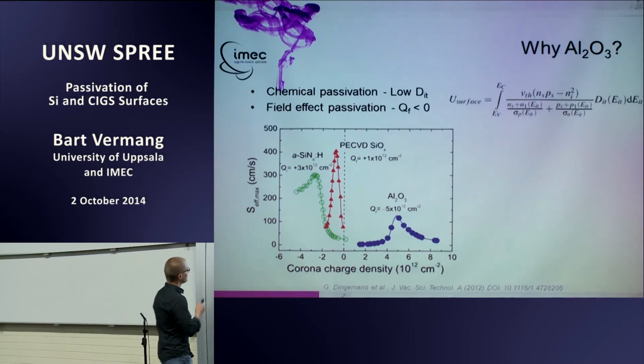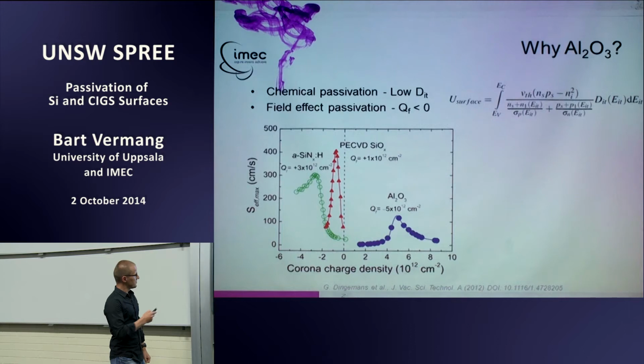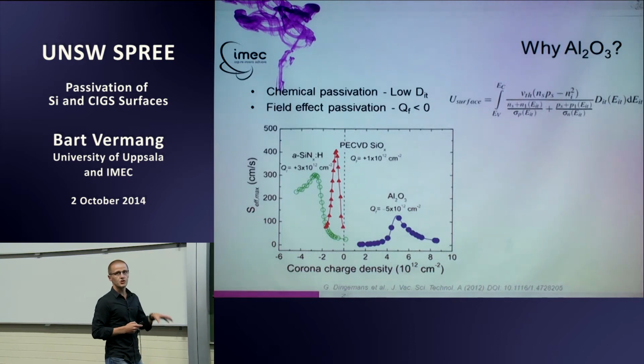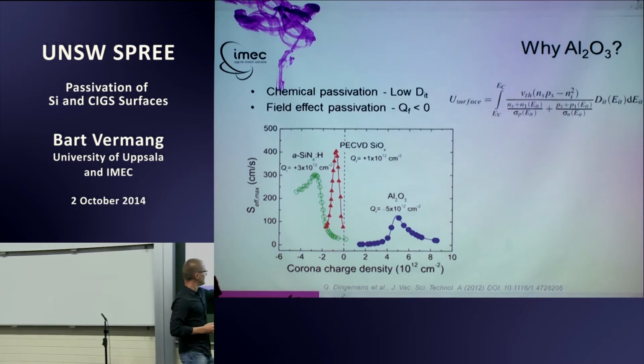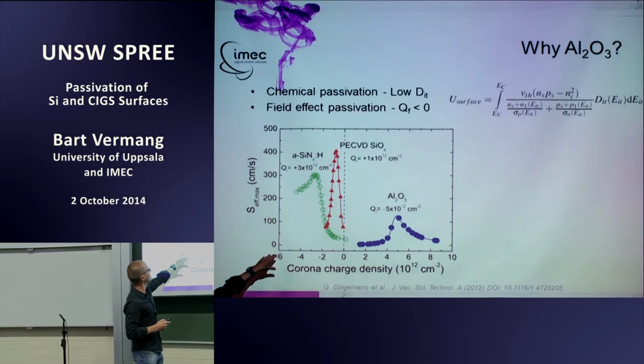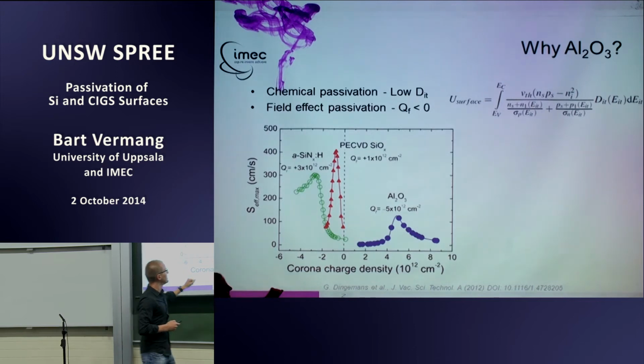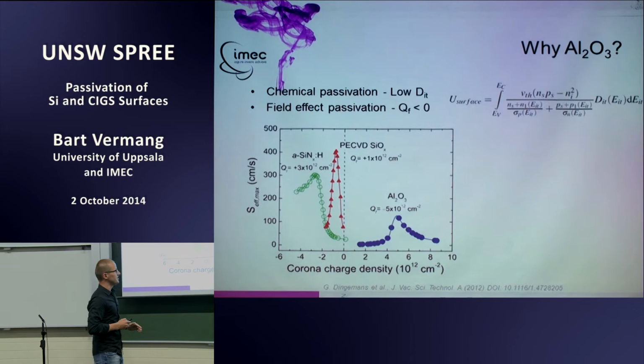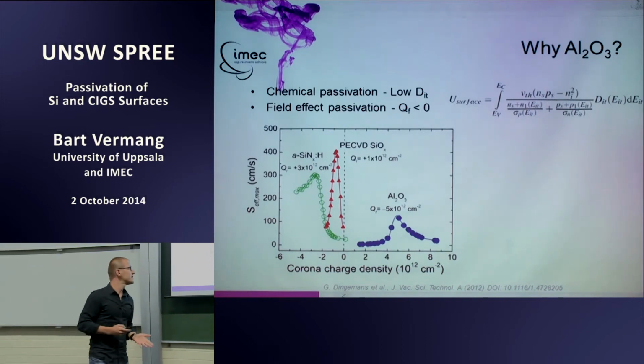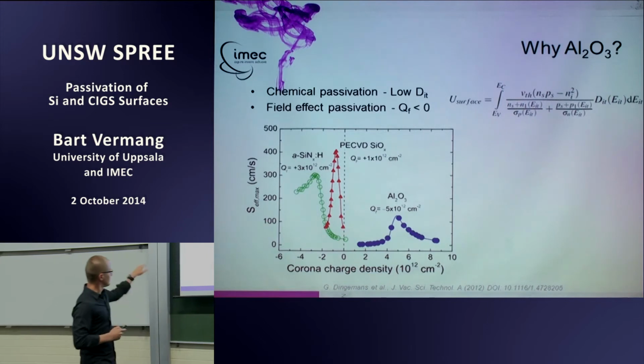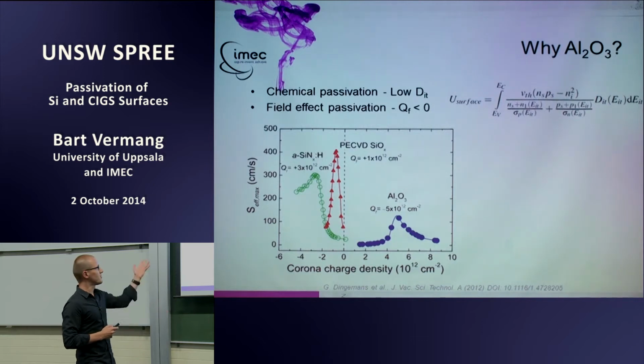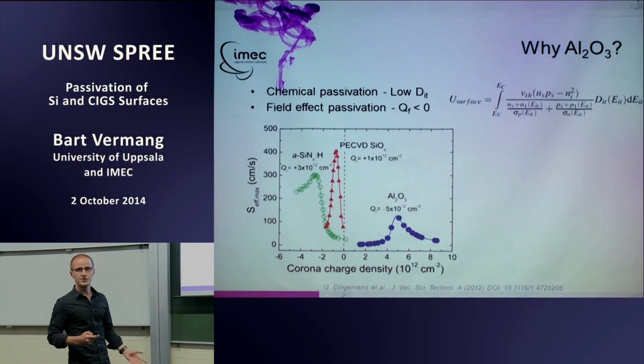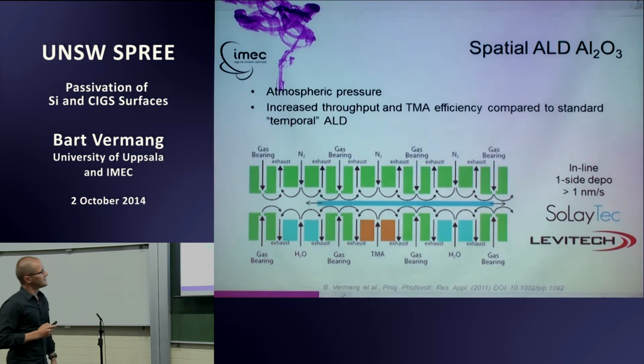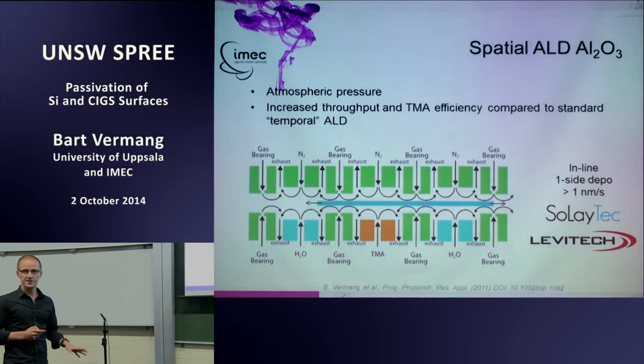Here, for example, you see rear surface recombination velocity as a function of corona charge density. This is a charge applied on top of the passivation layer. And you see, where you have a negative corona charge density, we have amorphous silicon nitride and silicon oxide. Where you have a positive corona charge density, we have aluminum oxide, which means in the aluminum oxide there is most probably a negative charge density. You see as well the surface recombination velocity is very low for aluminum oxide. It can be low for silicon oxide as well; they probably just used a low quality silicon oxide here. But negative charge density, that's an advantage of aluminum oxide. Spatial ALD aluminum oxide. So we have been focused at IMEC on ALD.